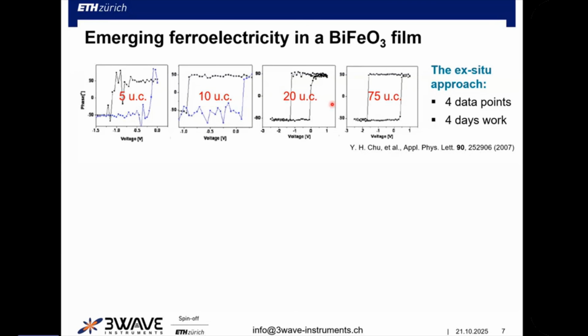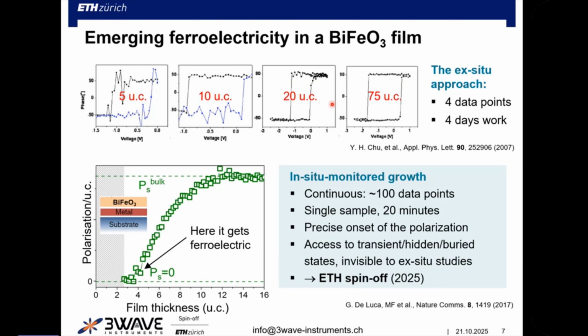Now, our approach is to do this while the sample grows. And here we see we get 100 data points in 20 minutes. So it's a speed up factor with many zeros. And you immediately see if you grow a ferroelectric bismuth ferrite film, at the 4th unit cell this frequency doubled signal emerges. So here it gets ferroelectric, the sample becomes ferroelectric. And then when you have like 12 unit cells, you have the saturation. So from here, the film is like a bulk crystal. And yeah, consider the timescales, 4 data points, 4 days versus 100 data points in 20 minutes. And really the one sample, not 4 or 100.